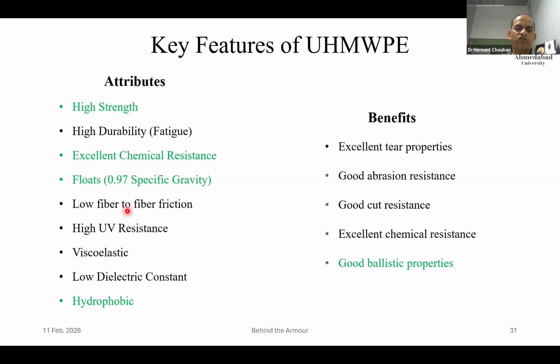They have low fiber to fiber friction. In case of, say, glass, the fibers interact and they abrade each other, or many other fibers as well. But since these have low surface energy, they give very low friction, so no damage. Not much affected by UV. That's a very good advantage. They are viscoelastic in nature, low in dielectric constant. For this reason, I've now started studies in that direction. It's a very good material for unmanned aerial vehicles, the drone body parts, or wherever we are looking for radar transparency.